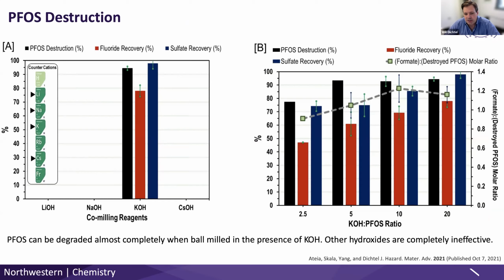We started looking at ball milling PFOS and found all sorts of interesting findings. First, we ball mill it with potassium hydroxide, which helps to degrade it. It really matters that it's potassium hydroxide. It doesn't work for even other hydroxides. What we're really focused on is studying how much potassium hydroxide you need, and what you get. Because if we just broke down PFOS into other organic fluorines or organofluorine compounds, that probably wouldn't be very desirable.